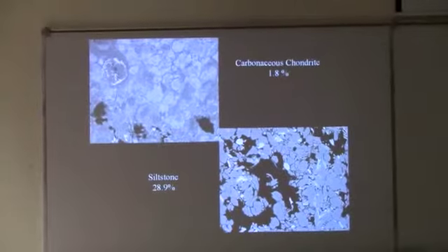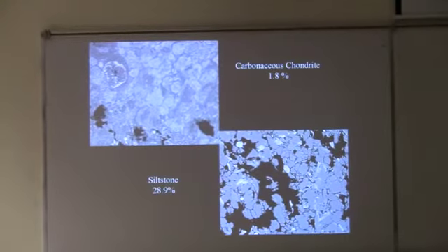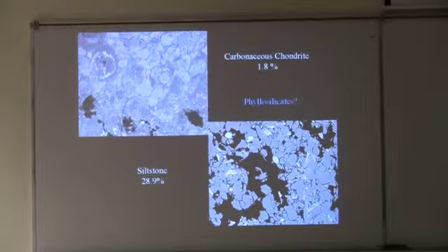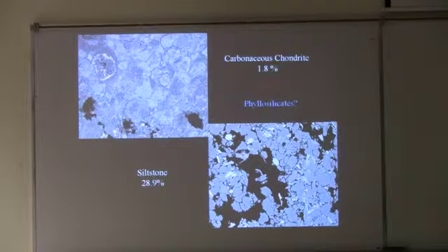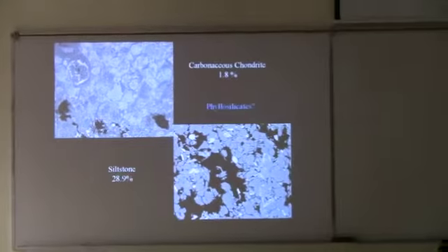So this is still a big question that we have in measuring these carbonaceous chondrites: where is the porosity? Carbonaceous chondrites are full of phyllosilicates, which are layer silicates, and we've proposed, well, maybe the helium goes into the layers of the silicates, which isn't true porosity, but it's going into the rock. But now Phil has told me that it comes right back out fairly fast, so maybe that's not the solution.